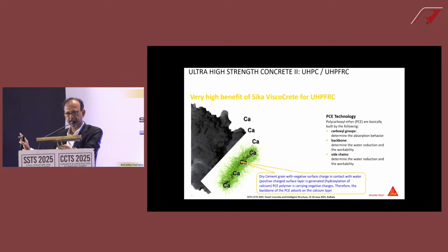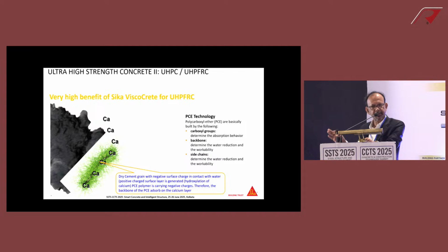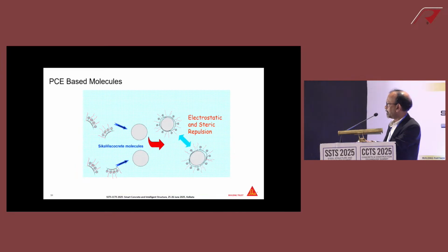This is very basic. Now, depending upon this, the extension is ultra-high strength concrete where the water cement ratio is 0.16 to 0.18, and you can still have good workability. You can also have good workability at 0.4. You can also have good workability if you add extra water at 0.5, but your durability factor is going to be 0. You will have corrosion problem, carbonation attack, chloride attack. So all of this is a function.